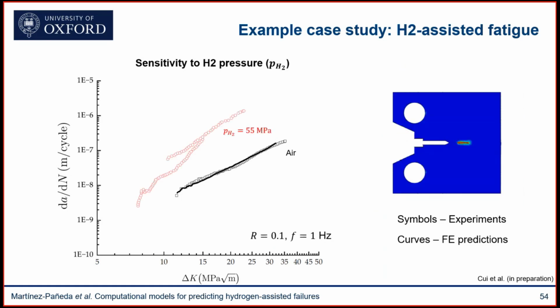Now there is data for hydrogen for multiple pressures. They have data for 55 megapascals, for example. So we said, okay, now let's not touch anything in our model. And let me emphasize this. I'm not touching any parameter of my model. My model remains exactly the same. The only thing that I'm doing to my model is that I'm enabling hydrogen diffusion. I know what the hydrogen concentration is that corresponds to this pressure of 55 megapascals. I'm putting that as my boundary condition. I'm pre-charging my sample a little bit, 24 hours, as they do in the experiments, and then running my test.